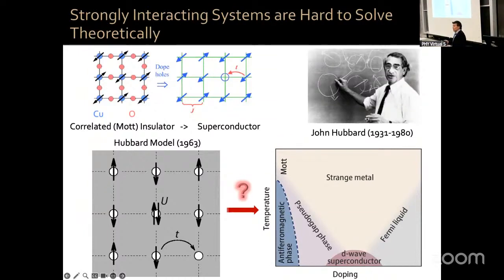Now, they would like to explore the entire phase diagram, and in particular, try to reach this region of d-wave superconductivity, d-wave superfluidity due to repulsive interactions in the cold atoms case. However, one big technical challenge that the cold atoms community has is that they're currently working in a very high temperature regime. I say high temperature, but in reality, they're working at about a nanokelvin. But that is high temperature for cold atoms and the energy scales of the system. So they would like to cool down.